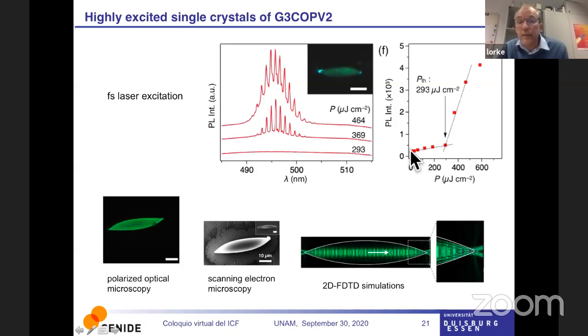A better sign yet is a threshold behavior where at low excitation you get a linear increase in the emitted light. And then at some point when lasing starts, you get a much higher slope, and that's why lasers are so efficient, because they very efficiently convert the excited electrons or electron hole pairs back to light, and that's why the slope here is much higher.